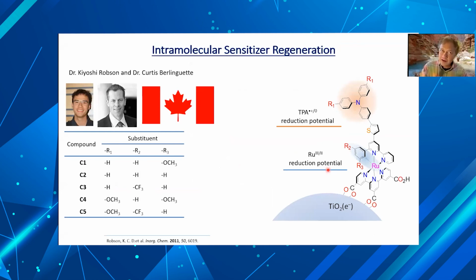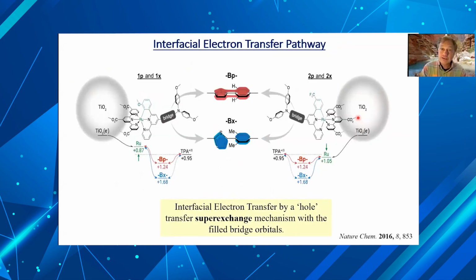In both those cases, it was hard for us to understand because we had a flexible spacer where those donors were. And we became aware of this work of Kiyoshi Robeson and Curtis Berlinguette in Canada, where they had a more rigid type spacer, an aromatic spacer between the two. And what we found in their studies was that the nature of that bridge, that aromatic bridge, whether the thiophene could become coplanar with the phenyl or whether it was at a right angle, had a big impact on the recombination electron reaction. And that was a little surprising to us. We didn't expect that these electrons would see a bridge molecule so far away, but they do. And there's a pathway by which the electrons would come back, in this case, to these oxidized triphenylamines.